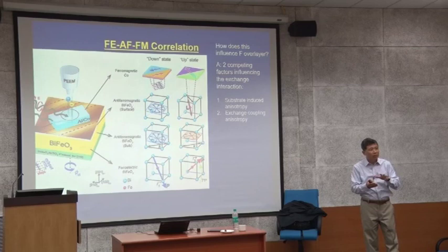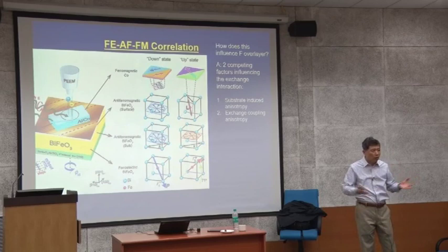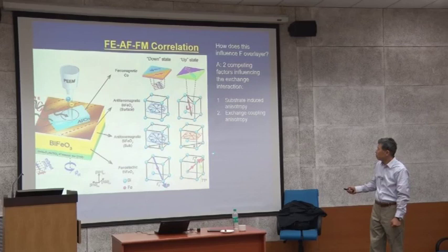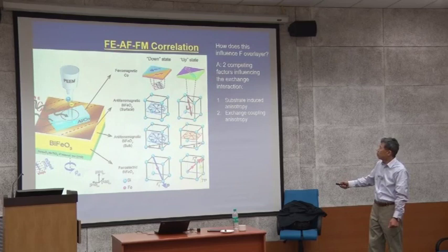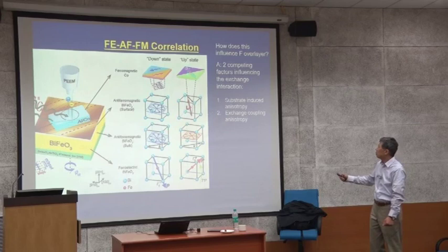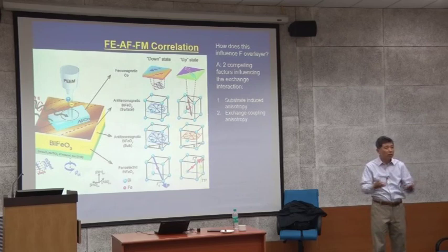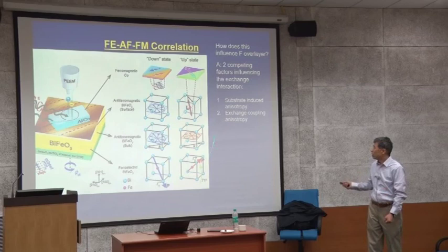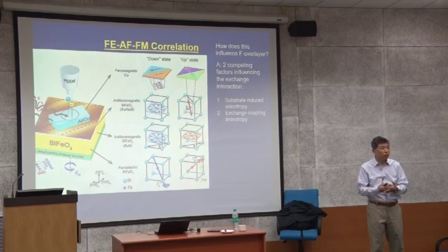The reason I emphasize this approach is that using a single monodomain, you study all the switching between the down and up states of polarization. You can measure the spin cycloid, the antiferromagnetic state, the bulk regions or interfacial regions separately, and at the same time you can look at the ferromagnetic layer on top of this, measure it by XMCD, and see the relationship and determine the mechanism. But without this monodomain, this is not possible. And this in situ measurement by synchrotron really allows you to do this. So I think for any ferromagnetic system you really want to study, for fundamental and important mechanisms, this elemental-specific synchrotron-based XMCD and XMLD is very useful.